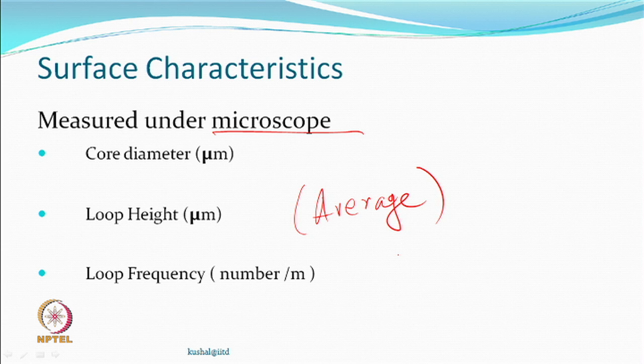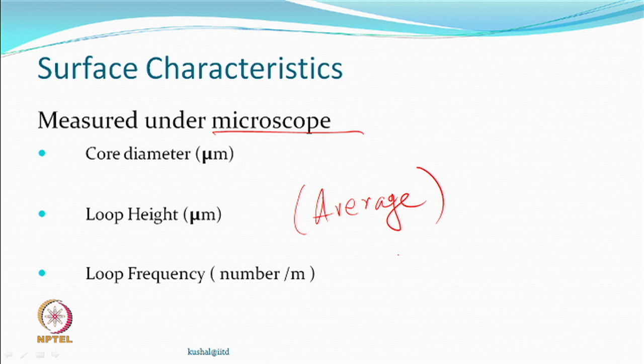So, this optical method in general will not really be used to describe the bulk, because we said last time that larger loops contribute to the actual bulk, in reality, less than the smaller. So, if you watch under a microscope, it will probably give you the impression that it should be much bulkier, but in reality it may not be, but this at least can be used to explain certain observations which may have been otherwise unexplained.